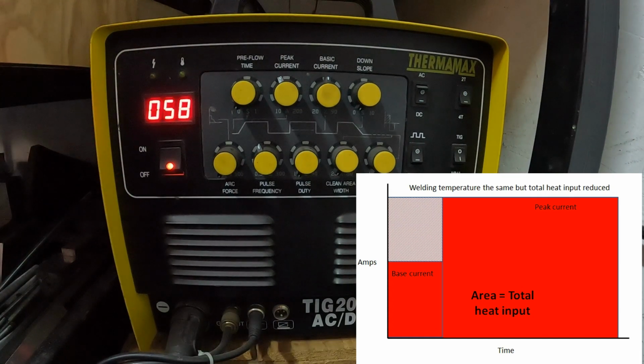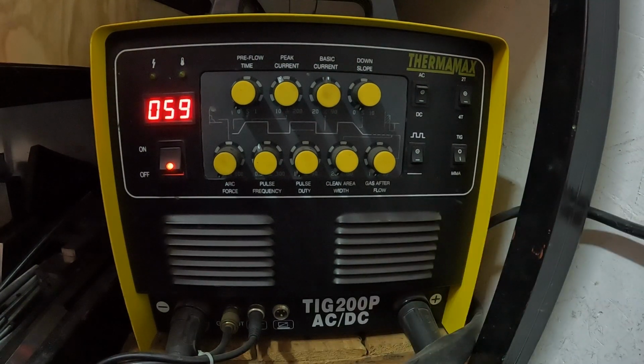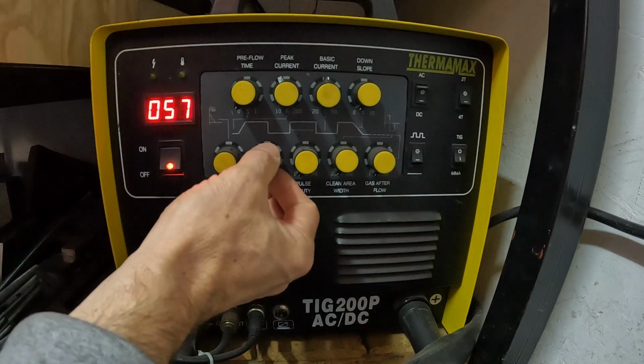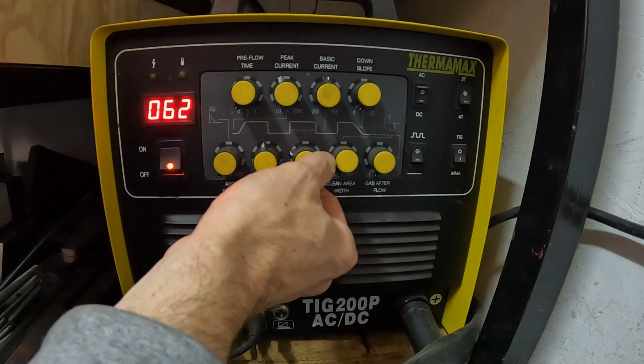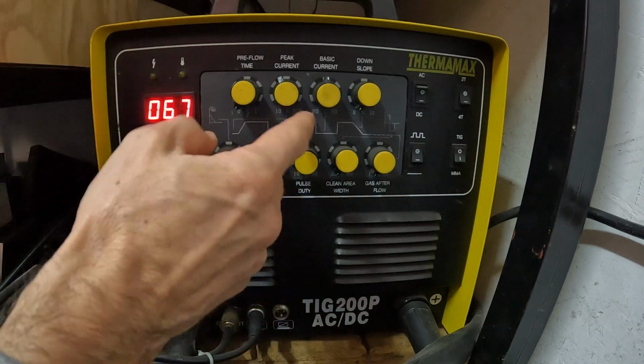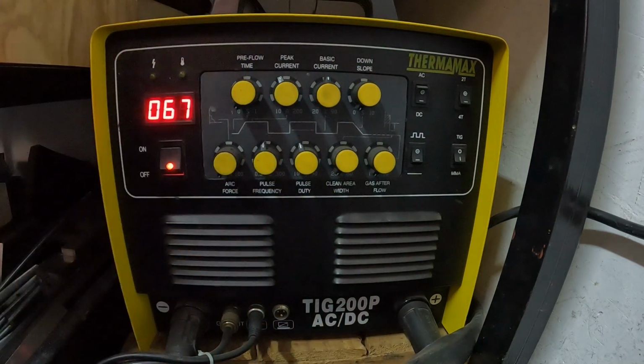So again, what it does there is it just increases the time, or increases the amount of heat that you're putting into the material that you're welding. Now let's think about this practically, right? If you're welding stainless steel, as I mentioned, you've got a high temperature arc. You don't need as much heat input because the material doesn't get rid of the heat as quickly, because it's lower conductivity. So you can get away with quite an aggressive pulse frequency with a 50% pulse duty, a peak current, and then a basic current of, let's say, half. And you're going to halve your heat input into your weld.